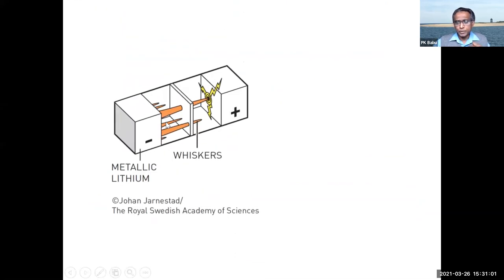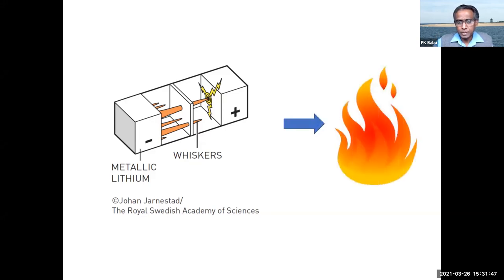These whiskers will start growing. They will penetrate the barrier between the positive and negative half, and they might even reach the cathode of the battery, and that will create a short circuit. And most of you know that short circuit offers a path with very small amount of resistance for the flow of electrons that produces high current. Even though the resistance is small, the joule heating is proportional to I squared, so a huge amount of heat is generated. With an organic solvent, that would immediately generate fire. Not only that it caught fire, in most cases, the battery exploded.